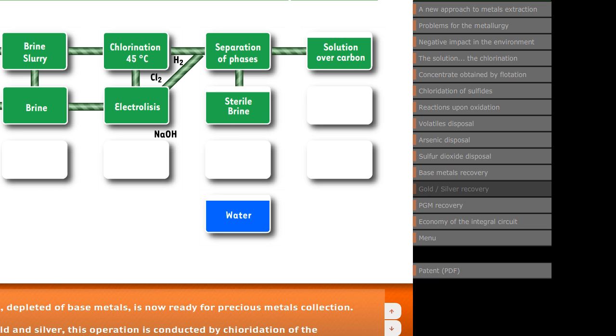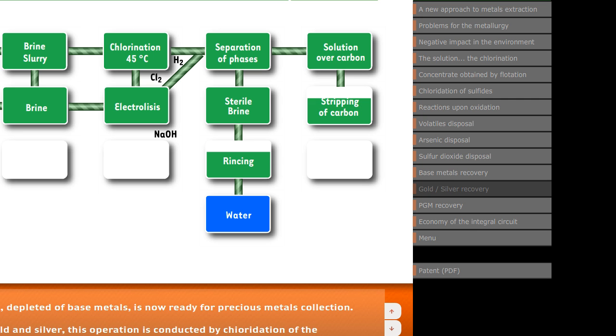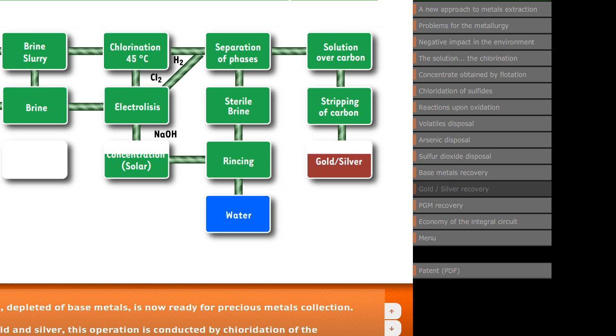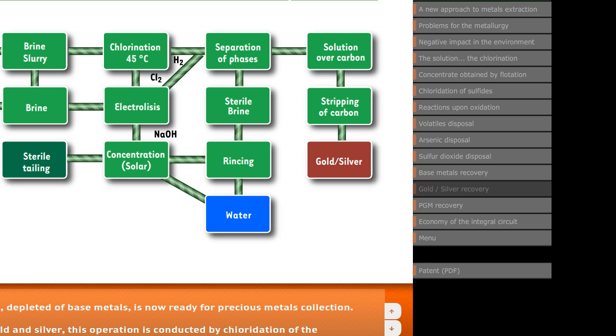The duration of this chloridation is very short, from 30 minutes to a few hours, and the consumption of chlorine is very small due to the previous leaching of base metals. If silver is present, the chlorinated mass is taken up with a brine of 250 to 300 grams of salt per liter, in order to ensure the solubilization of the silver chloride. The pregnant solution is then circulated over carbon for precious metal stripping, and the accumulated values are recovered by standard electrodeposition. The solid is rinsed and the brine is concentrated and recycled.